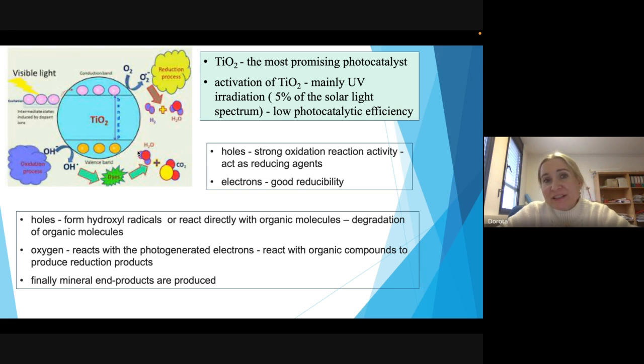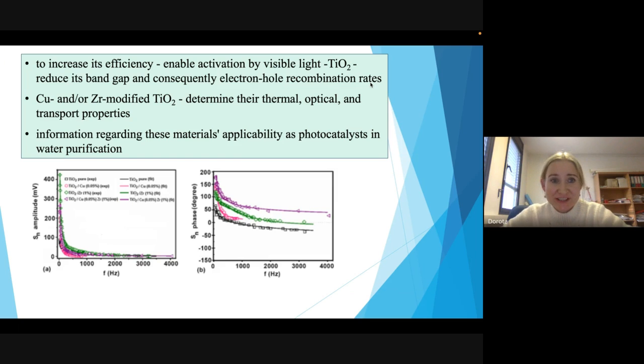So titanium dioxide is widely used, but it also has very serious disadvantages: its activation occurs mainly under UV irradiation. UV irradiation is only 5% of the solar light spectrum, which makes the pure titanium dioxide photocatalyst very inefficient. So a lot of effort is made to increase that efficiency. How to increase the efficiency? They want to reduce the energy band gap and reduce the electron-hole recombination rates.